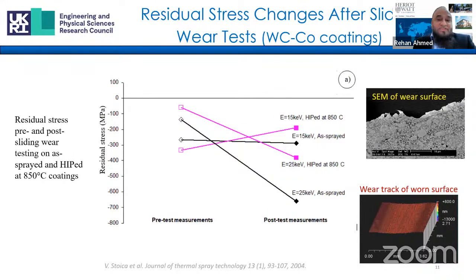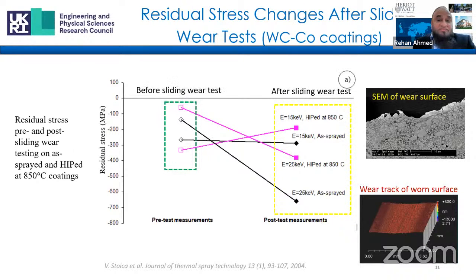This slide provides another example where the depth of residual stress measurement can be made specific to near surface measurement. And in this case, we use synchrotron technique. And this can be useful when interpreting changes in residual stress due to sliding wear or other near surface phenomena. So you have the residual stress values before the wear test and then after the wear test, basically. So measurements were done at two energy levels of 15 keV and 25 keV to change the depth of measurement